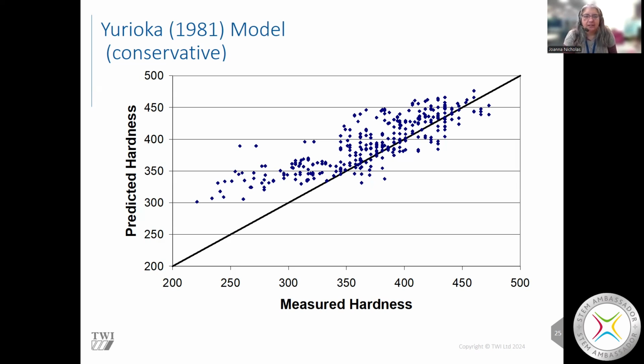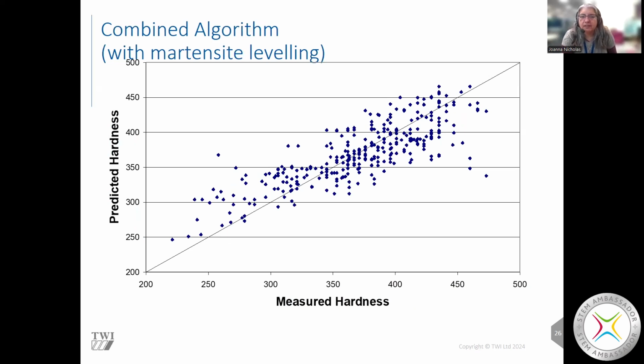So taking that unconservative and conservative model and combining the two, we actually get a much more even distribution. And this then showed that you could use this empirical model for these about 300 data points. And it worked for those data points reasonably well, with some caveats: for about 50% of the items the model predicted a lower hardness than it should be, and for 50% a higher hardness than it should be. But the spread was quite good. Standard deviation was 25 hardness points, so two standard deviations, 50 hardness points. So it was a usable model as an empirical approach.